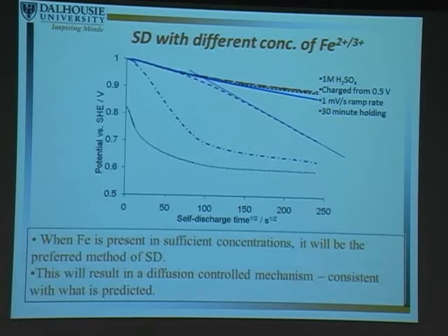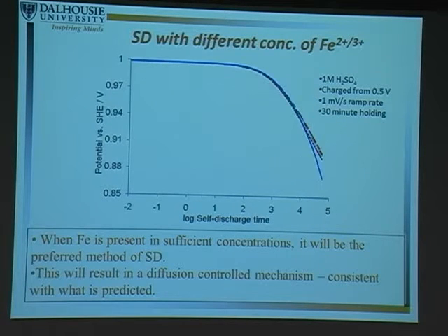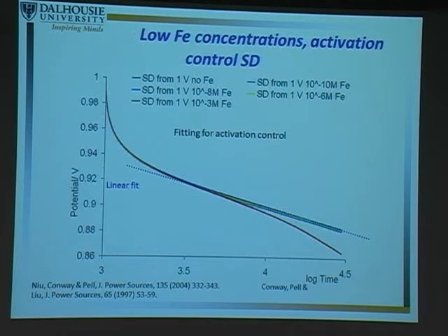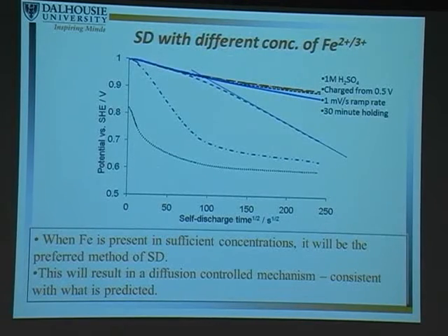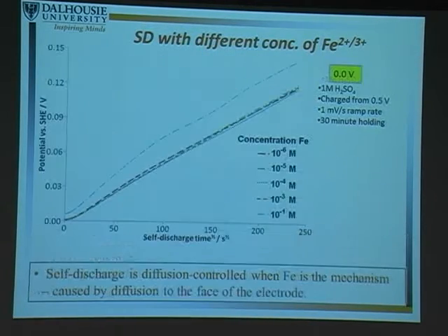Let me just highlight one other thing. With the positive electrode, as we look at this profile, at 10 to the minus 3 or 4 molar, we still see a big drop in our voltage, even when there's no iron. So iron can be a problem, but a lot of the self-discharge that we're seeing is not actually due to iron. It's due to something else.